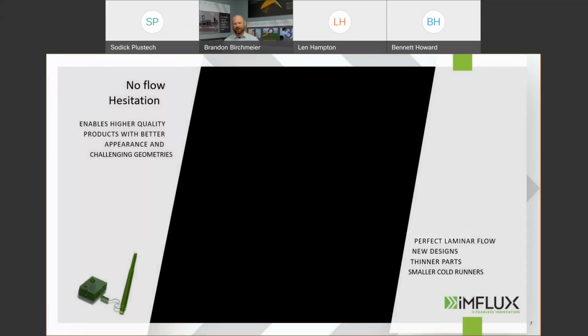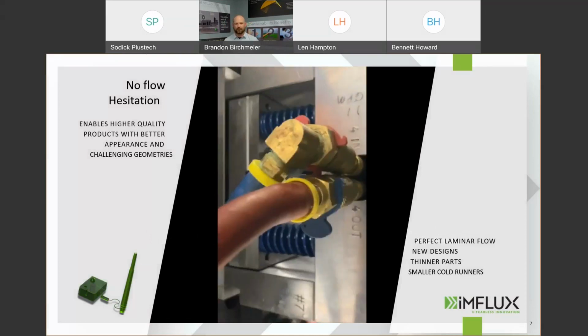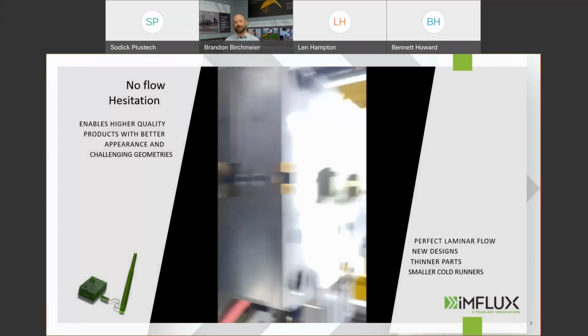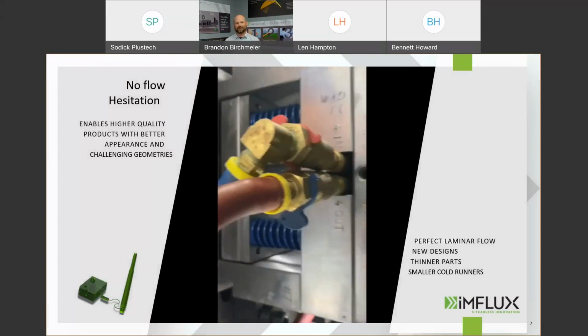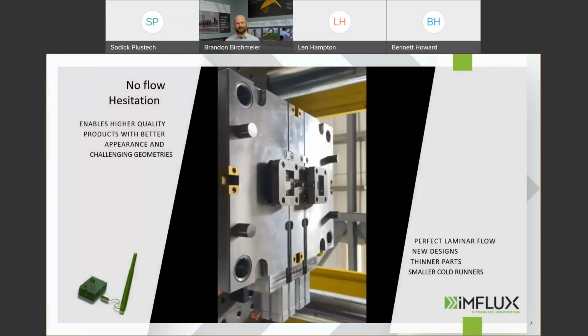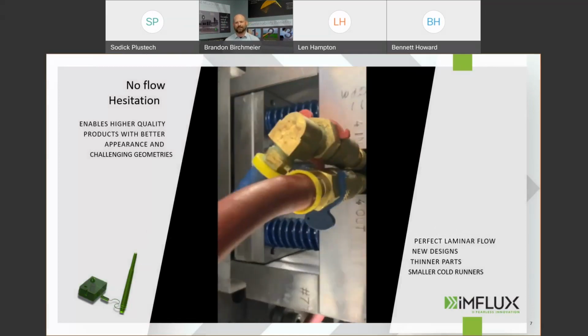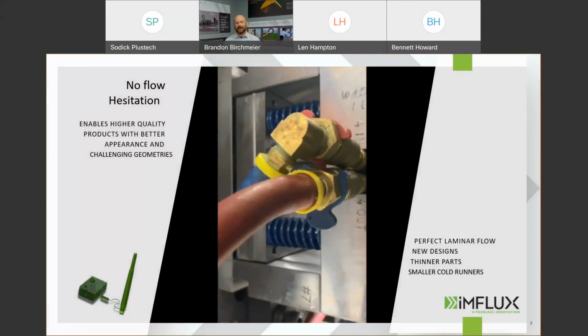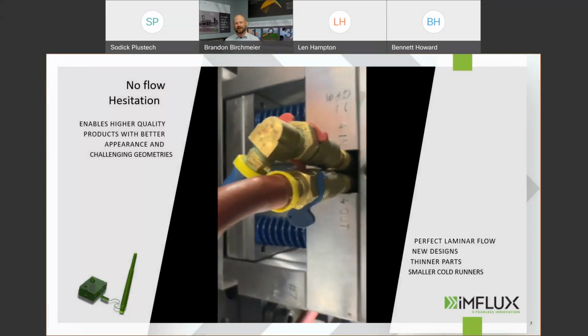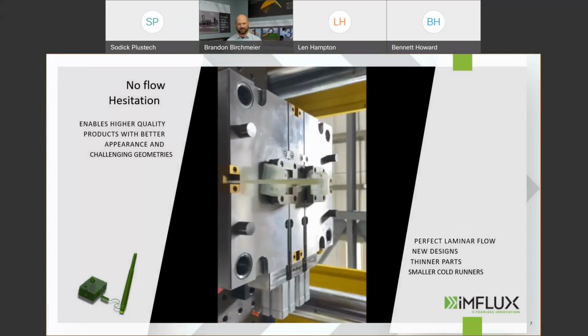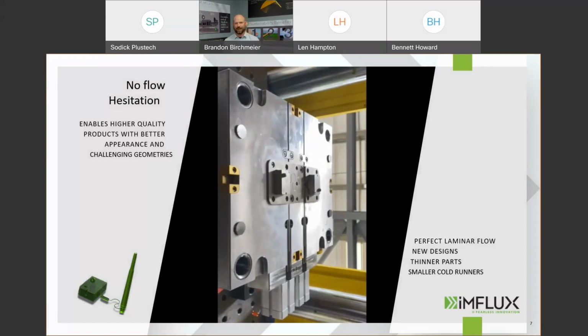The first is you can do some pretty wild things when you always allow the plastic to be in control, which is what's happening here. So in this part here, this is one of our impossible parts that has been featured in Plastics Technology. We've had it at trade shows as well. What you're seeing here is a pretty big, typical sprue system that goes down to a 3-inch long, 30 thousandths diameter runner system. So it's like a thread for a runner. Then goes back into a subgate into a full part.